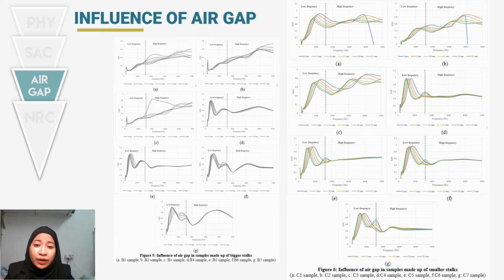Last but not least, the samples of C4, C5, C6 and C7 only influence the value at a low frequency range, whereby the highest peak is shifting towards a lower frequency range. Besides, it creates a new peak within the frequency of 1000 Hz to 2000 Hz as the thickness of the air gap increases. If compared with and without air gap, the value with air gap is lower at the same frequency. The range difference of the highest peak between with and without air gap in these samples showed that it is less than 0.05. This low range indicates that the air gap does not influence the value of samples C4, C5, C6 and C7, although a new peak is introduced.